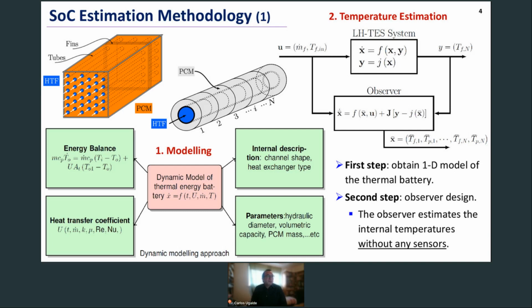The first step involves obtaining a dynamic model of the thermal battery. This process is summarized by the block diagram at the bottom left of the slide. This is not a computational fluid dynamics model, but instead a simple dynamic representation. The modeling requires an internal description of the shape of the channels where the heat transfer fluid circulates, and other attributes such as the heat transfer area. It is also necessary to have knowledge of the thermophysical properties of the heat transfer fluid and the PCM so that we can calculate the heat transfer process accurately. This way, we can also obtain the heat transfer coefficient and we can establish energy balance so that we describe the thermal battery behavior.